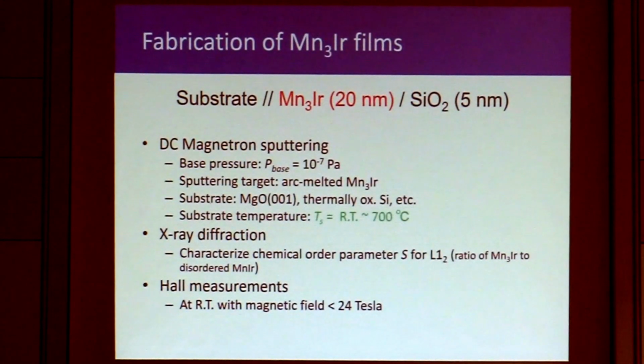The fabrication of the manganese 3 iridium film is as follows. We make a single layer of manganese 3 iridium, 20 nanometers, capped by silicon oxide, using magnetron sputtering and an arc melted manganese 3 iridium target. The substrates we are using are MgO 001 and thermally oxidized silicon. We vary the temperature from room temperature to 700 degrees C. For characterization, the chemical order parameter for the L12 phase was characterized by XRD. And for the Hall measurement, we use a magnetic field up to 24 Tesla.